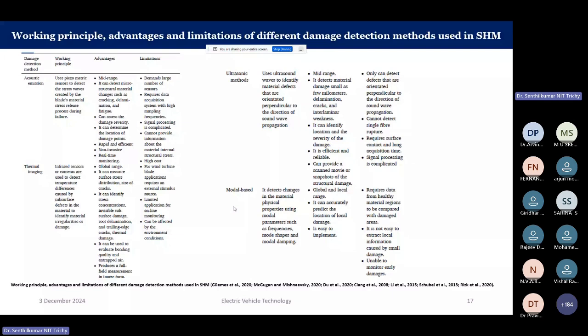So some methods, the damage detection methods, are used as ultrasonic methods, which use ultrasound waves to identify the material defects that are oriented perpendicular to the direction of sound propagation. So the advantages we can claim are mid range, it detects the material damage as small as a few millimeter delamination, cracks and interlaminar weakness. It can identify location and the severity of the damage. It is efficient and reliable. Can provide scanned movie or snapshots of the structural damage.